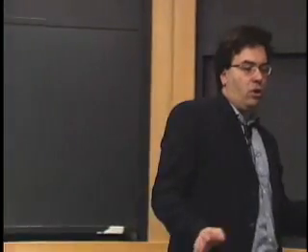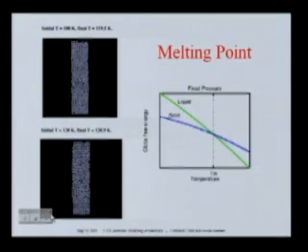And so your goal is being able to calculate the Gibbs free energy of your solid system as a function of temperature and the Gibbs free energy of your liquid system. And of course, the point where these two free energies cross is your coexistence point. Above that critical temperature, the liquid phase is more stable, and below that critical temperature, the solid phase is more stable.